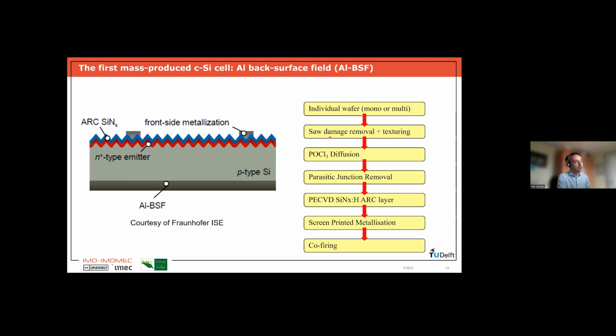So typically, you need to texture the wafer. That's one step you have to do. You have to diffuse phosphor inside of the wafer at the front so that you have the PN junction. Now the phosphor is also typically diffused at the sides and partially also at the rear. So there you have to remove it again. That's the parasitic junction removal. Then you grow by plasma enhanced CVD the silicon nitride layer at the front. And then we use screen printing of silver metal at the front and aluminium metal at the rear. And then you do a high temperature firing step.